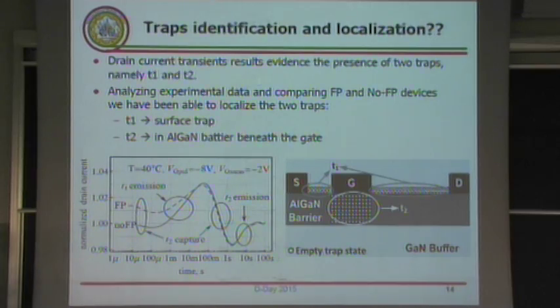What we saw is that after the switch on, the device does not achieve the steady-state value of the current instantaneously, but there were many processes like emission, which you can see here, and capture processes, and all these signatures are caused by the emission or capture of electrons from traps. Using experimental data, we were able to localize and identify two traps, one on the surface of the device, namely T1, and one located in the AlGaN barrier beneath the gate. Unfortunately, today I do not have enough time to show you the whole localization procedure, but it is just based on the observation of drain current transient measurements and experimental data interpretation.